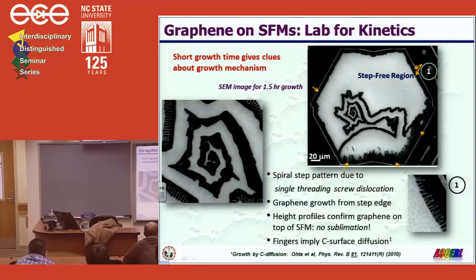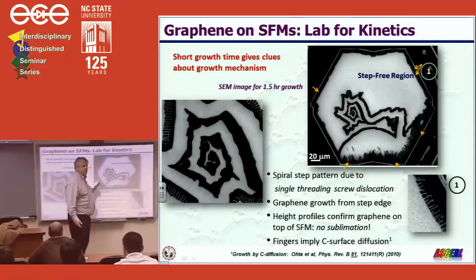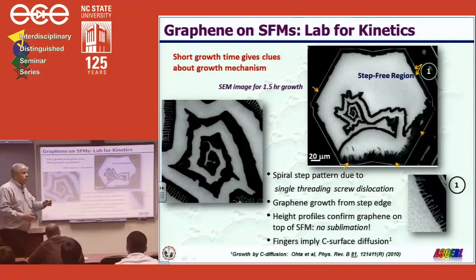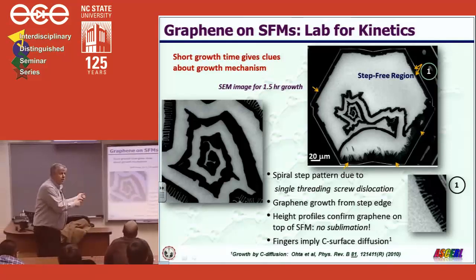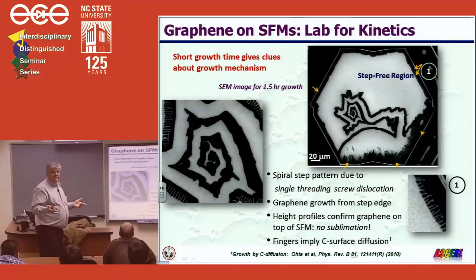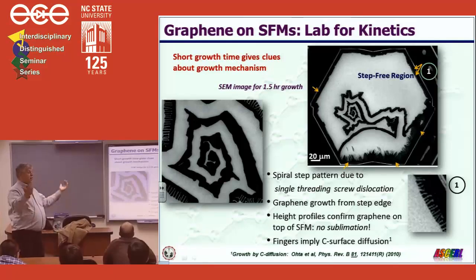And if the screw dislocation was not present here, that means the carbon's all coming from the edge of the sample and growing in. And so now, remember the original Raman that I showed you, where near the edge you had 3 or more layers? It all makes sense because you're starting from that edge and going in, so you expect the edge of the mesa to be thicker than the center.